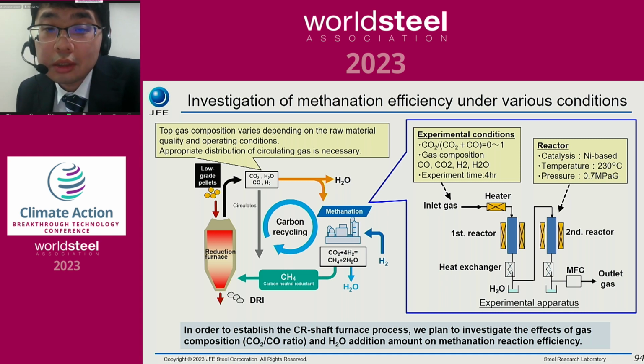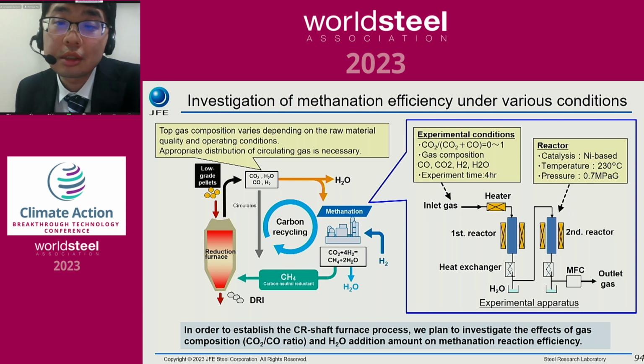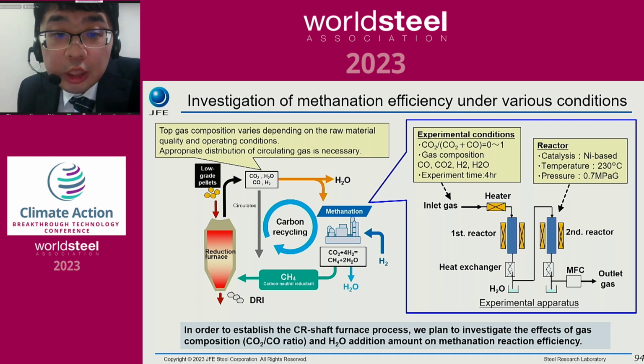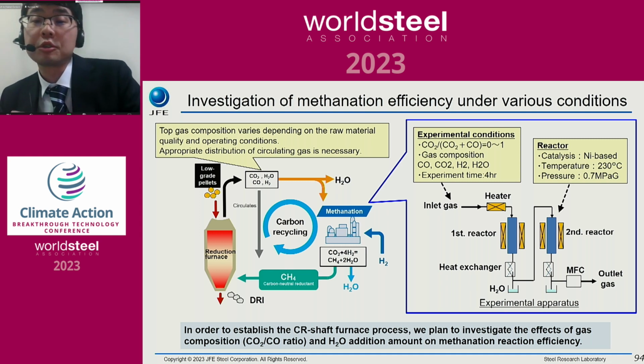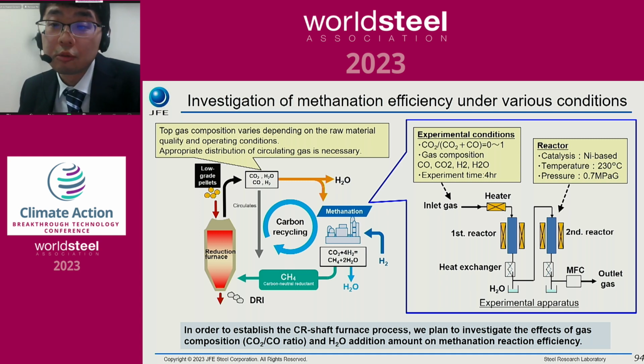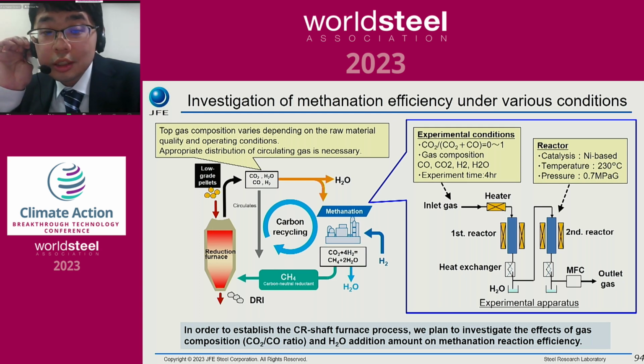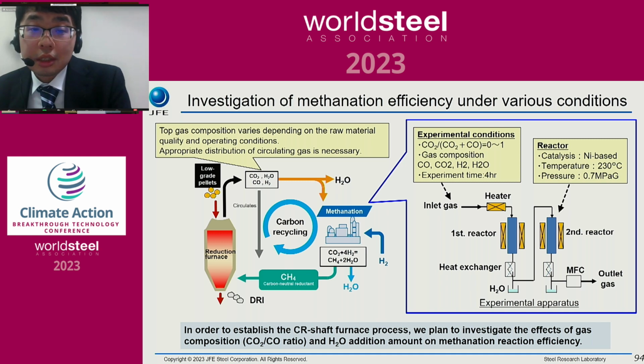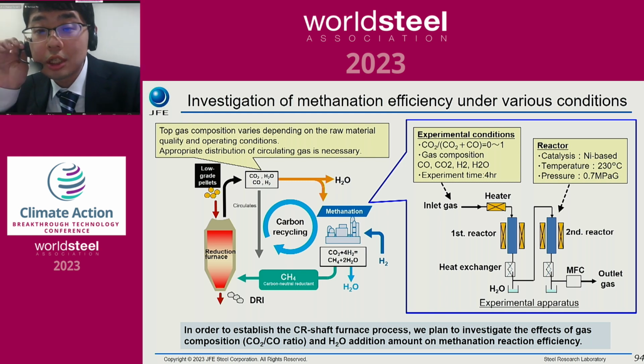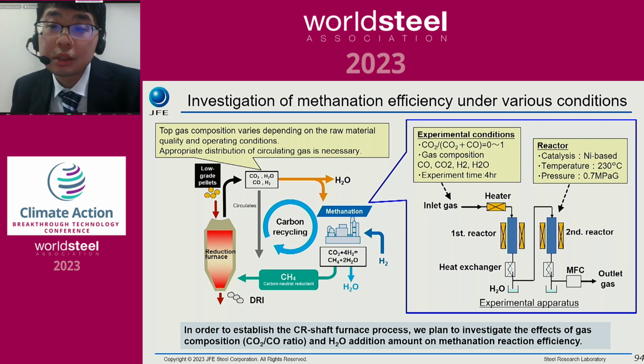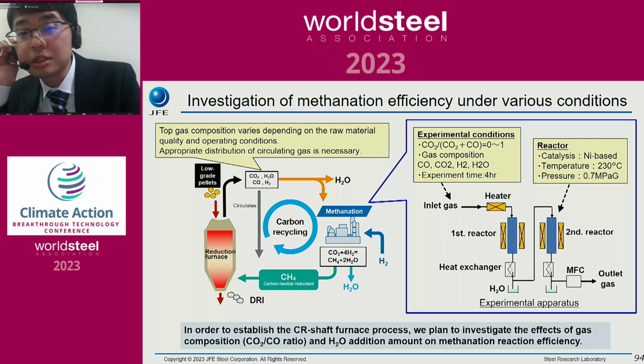The right figure shows the schematic diagram of the experimental apparatus of the methanation test. In the experimental system, two methanation reactors were installed. The experimental conditions are shown in the upper part. We plan to test the reaction efficiency when the ratio of carbon dioxide to carbon monoxide is changed and the effect of the addition of water. And the catalyst is a nickel-based alloy, and methanation is operated under high pressure. And by using this experimental system, good operating conditions will be proposed, assuming that the shaft furnace is equipped with a methanation process.